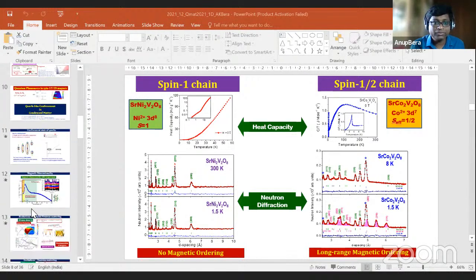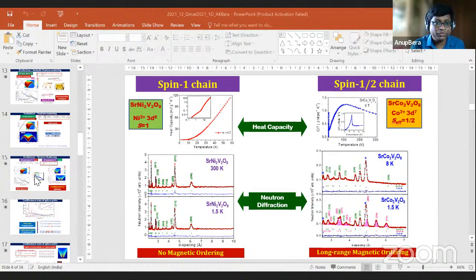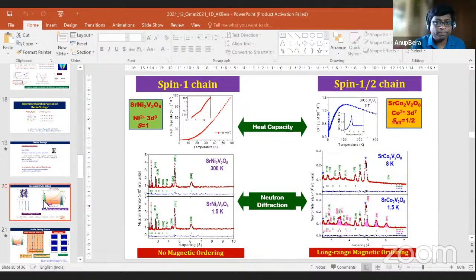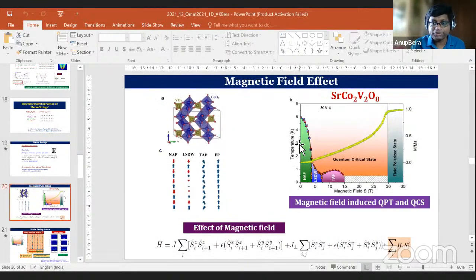And if I go back to my phase diagram, I show you here that we are in zero field. So this is the perfectly 1D state. What you are saying, what is expected for a perfect 1D spin half chain, we see above 5 Kelvin, but below 5 Kelvin, we see the Néel antiferromagnetic state is stabilized. But this state is not very strong. We can apply a magnetic field and destroy this state because the interchain couplings are weak.